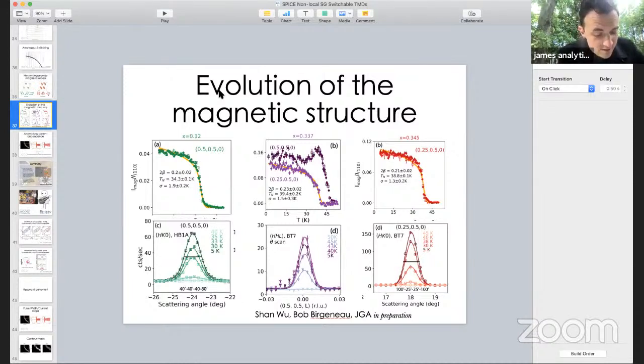Our strategy is basically the myriad measurements that we've done. We've looked at neutron scattering to understand the equilibrium state. We've looked at the NMR, the nuclear magnetic resonance, to understand what the local environment looks like as a function of disorder.